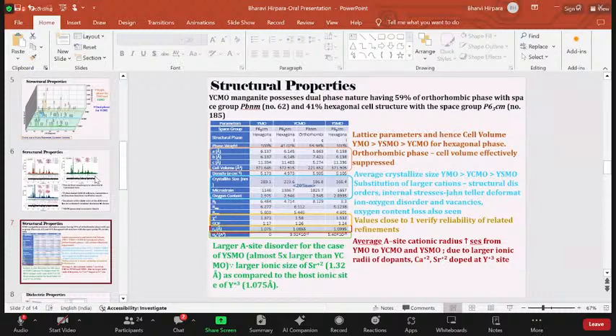It consecutively decreases also due to the substitution of larger cations, that is structural disorders come into the picture, which reduces the stresses in the material and leads to Jahn-Teller deformation, and some creation of oxygen disorder and vacancies. And also we can see that this is reflected from the oxygen content value, that is oxygen content loss is also seen from YMO to YCMO to YSMO compound.